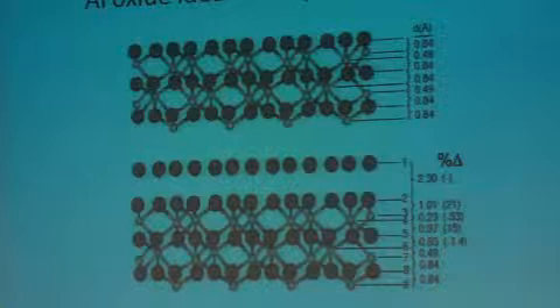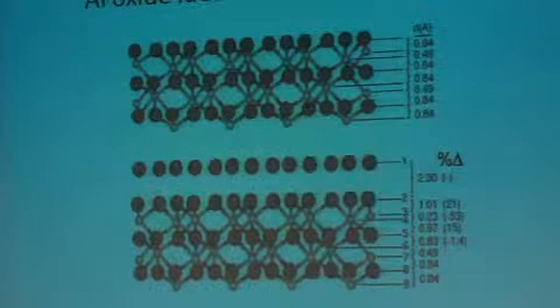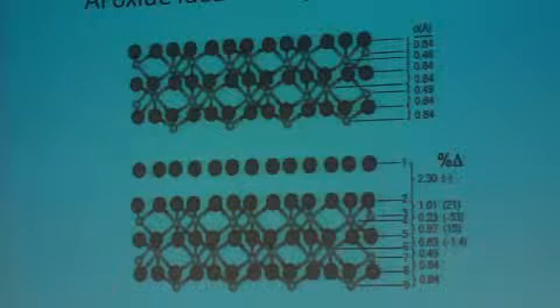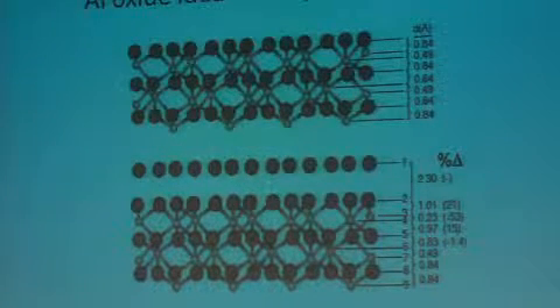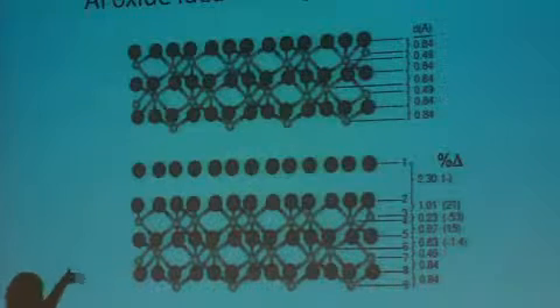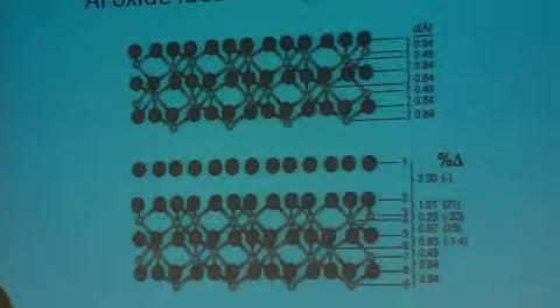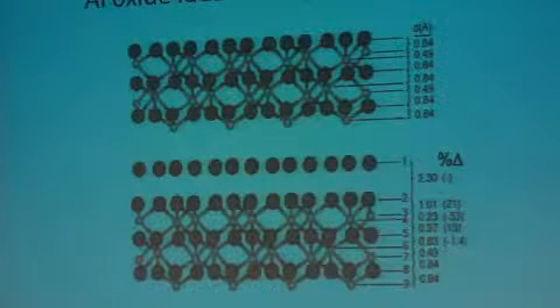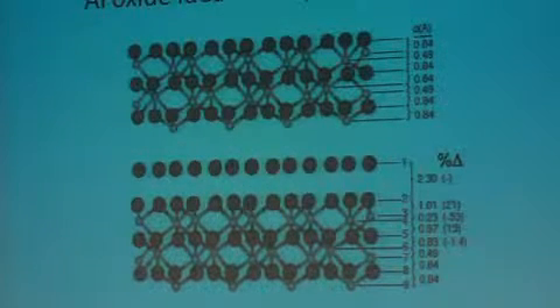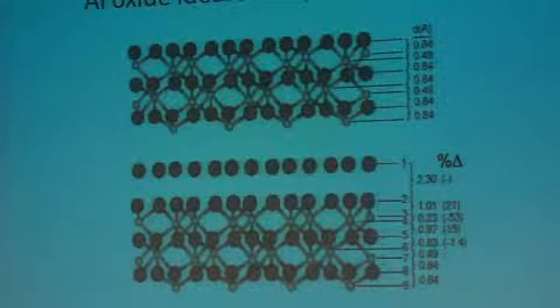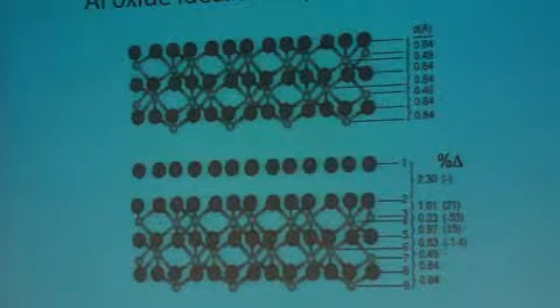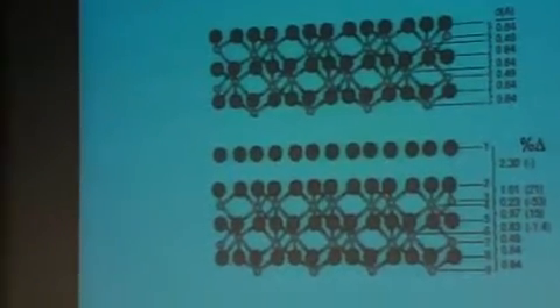So you've actually had some expansion and some contraction, some relaxation and non-relaxation, and that can penetrate down angstroms, at least angstroms, as much as a nanometer or more, depending upon the material. So what this tells us is that the actual bonding environment at a surface is different from in the bulk. Now, this is for a single crystal like centimeter scale. But when you've got a nanoparticle down at 2 nanometers, for example, as I mentioned before, basically the whole particle is surface perturbed. It's going to be different binding than in the bulk mineral, and that's going to affect its reactivity.